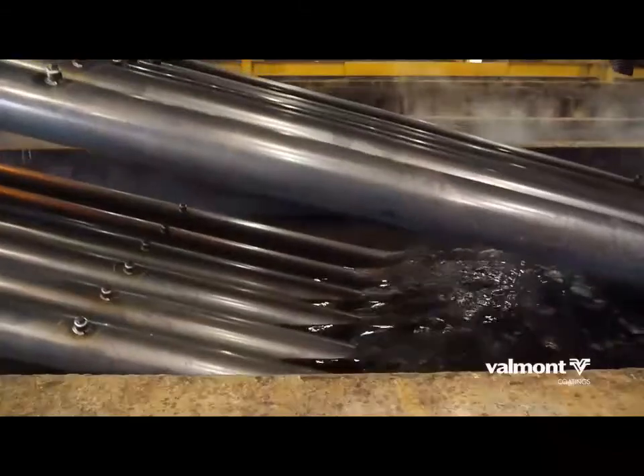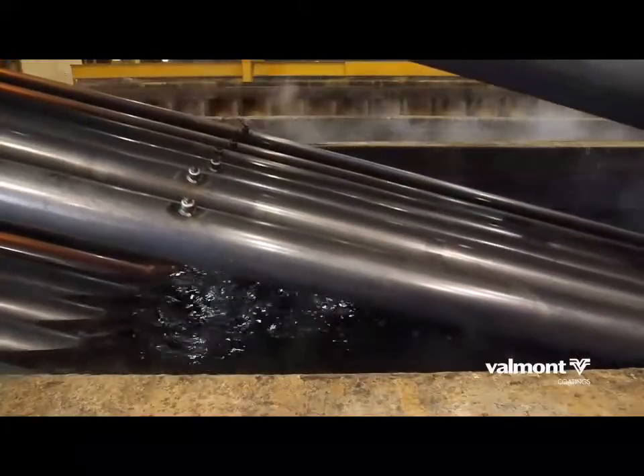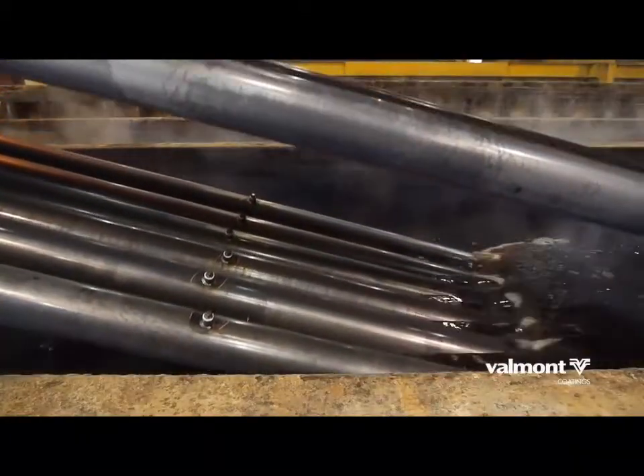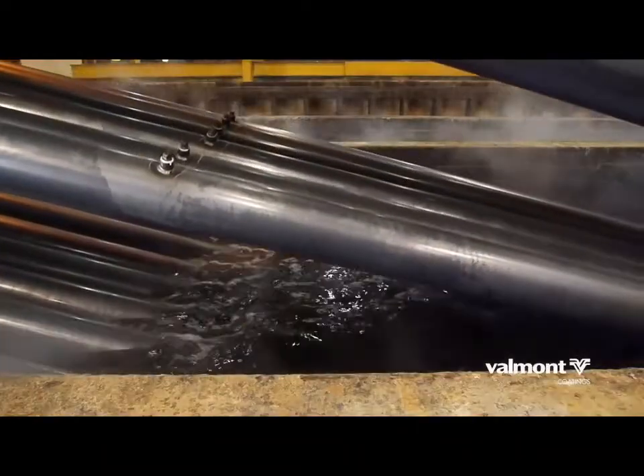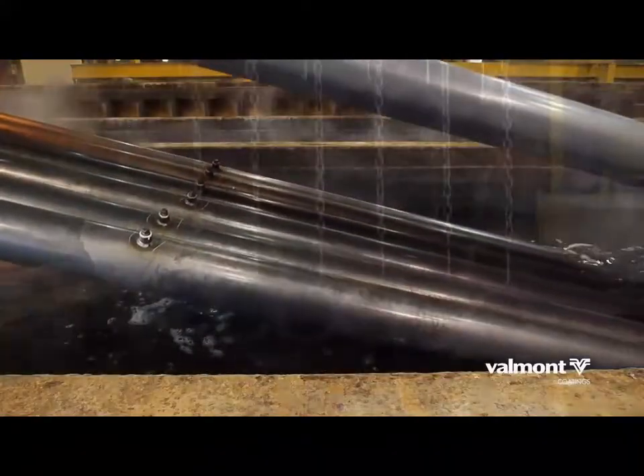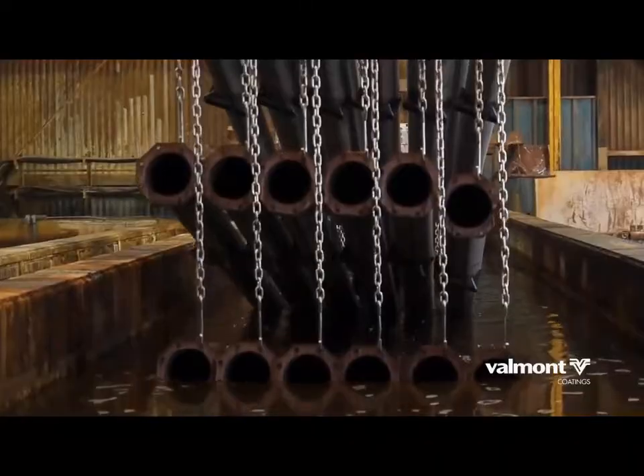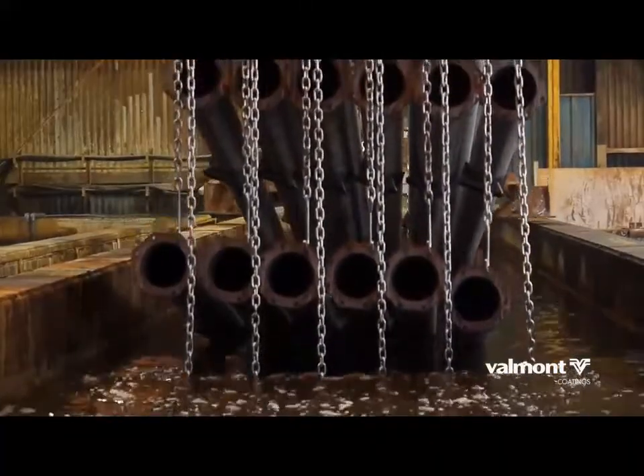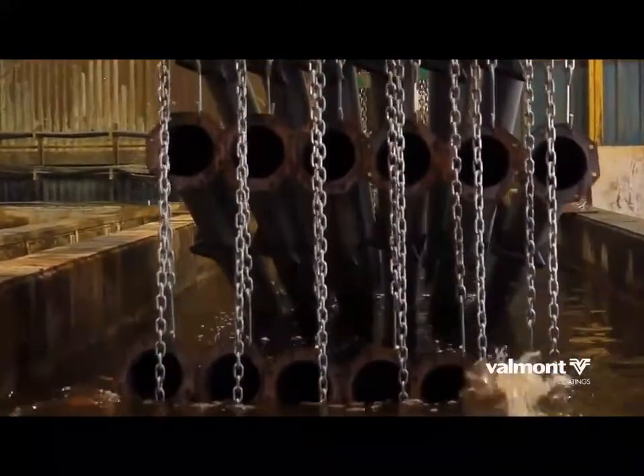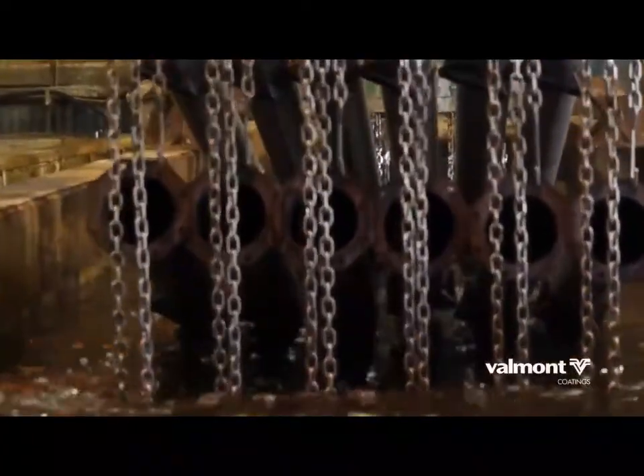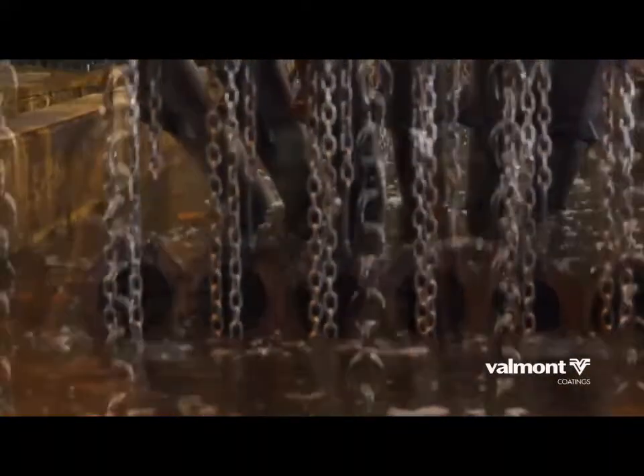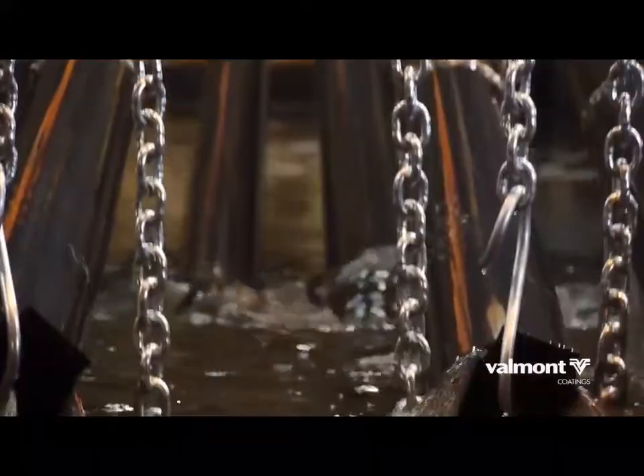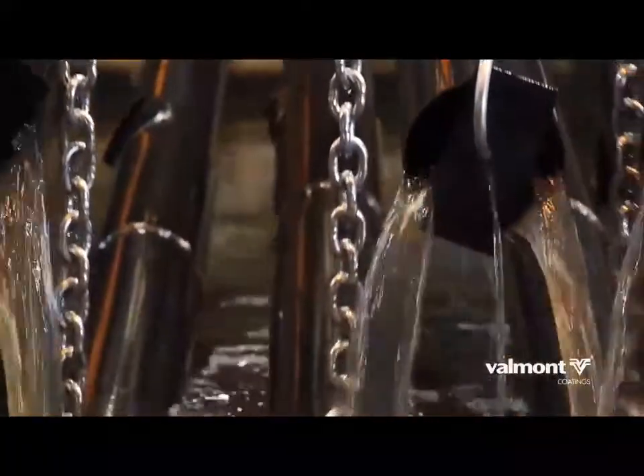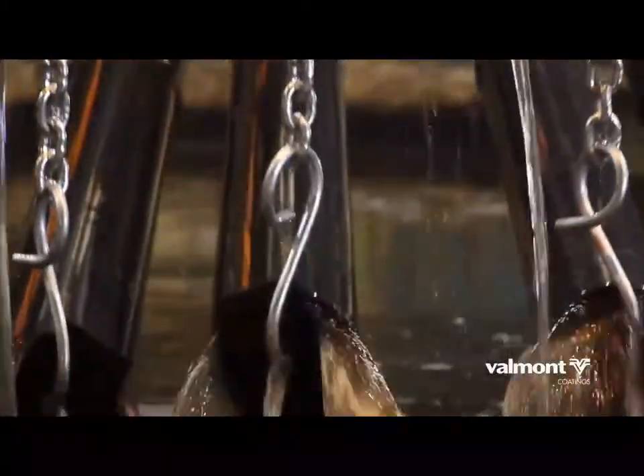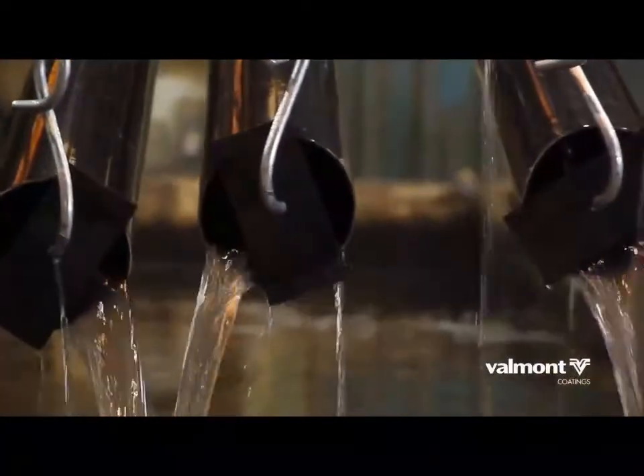The material moves through 3 cleaning steps to prepare the steel to be galvanized. Degreasing is the first step, removing dirt, oil, and organic residues. Then the structure is rinsed. The second step is a mild acid or pickling bath that will remove mill scale, iron oxide, and etch the steel. Then rinsed again. The third preparation step is fluxing. This step removes any remaining oxides and coats the steel with a protective layer to prevent any further oxide formation prior to galvanizing.